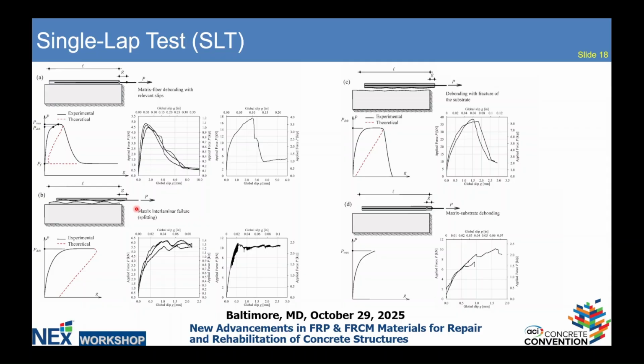You could have the slippage of the fibers, very common when the fibers are not coated. You can have the interlaminar failure, meaning the fibers will slip and drag with them the top layer of the matrix, and you create basically a shear crack, an interlaminar crack at the interface with the bottom layer of the fibers. You can have the typical cohesive failure of FRP. The entire package debonds from the substrate. You can have a clear debonding of the package. In other words, it debonds, but there is no cohesive failure. So the package is fairly clean and the surface of the substrate is still undamaged.